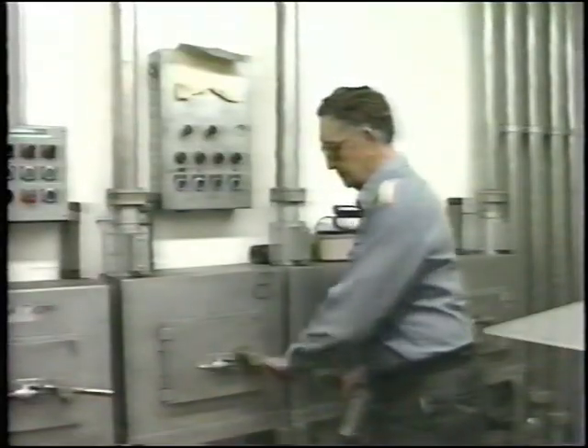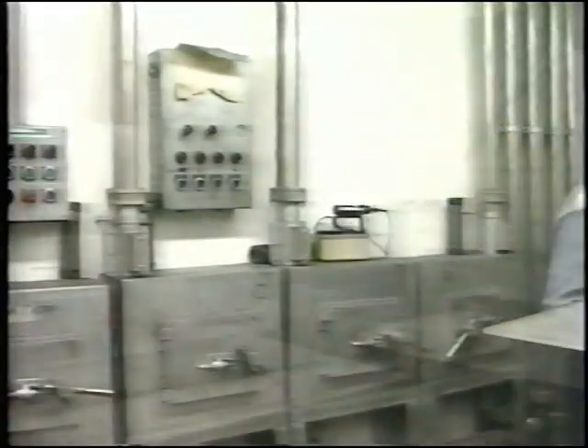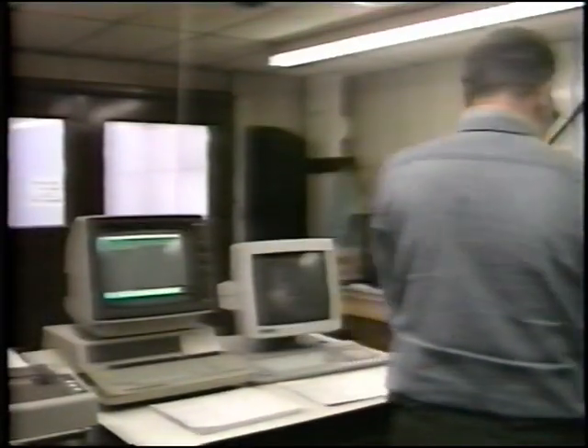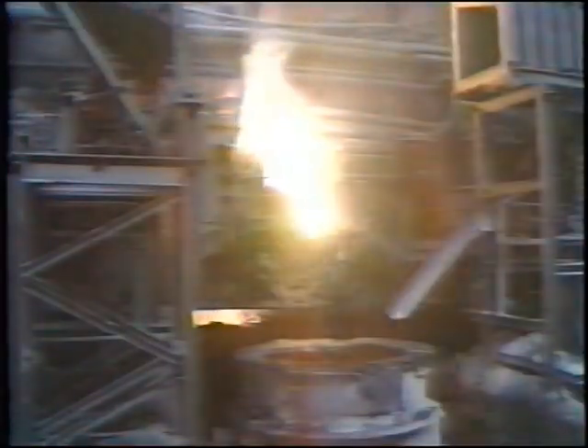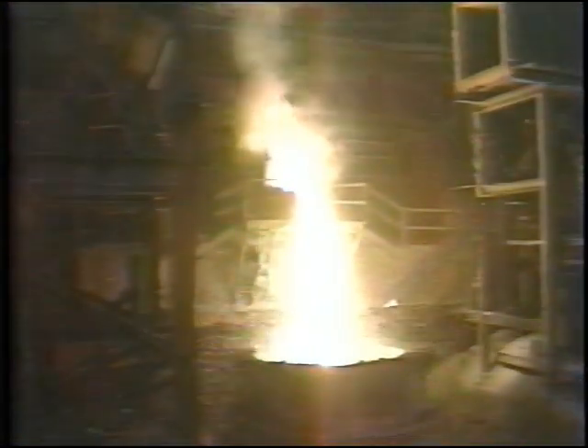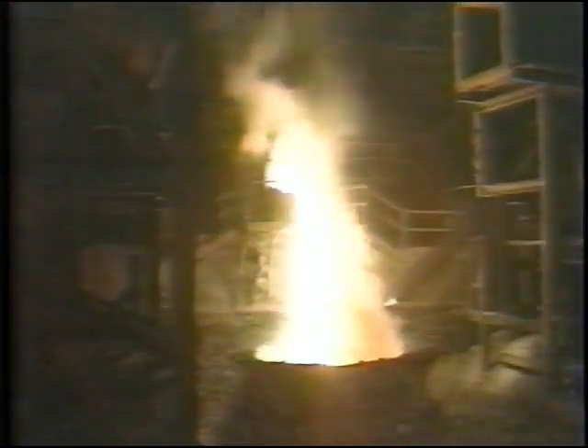Once pouring temperature is reached, a sample of the molten steel is taken to the metallurgy laboratory, where it's checked for proper chemistry. Then the entire furnace is tilted on rockers to begin the tapping operation. The molten steel is poured into the waiting ladle, and the ladle moves via its 500-ton crane to the stir station.